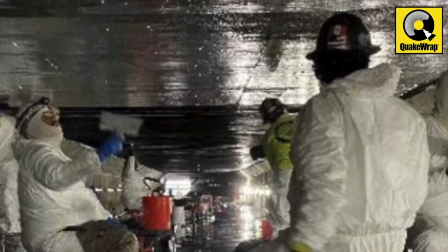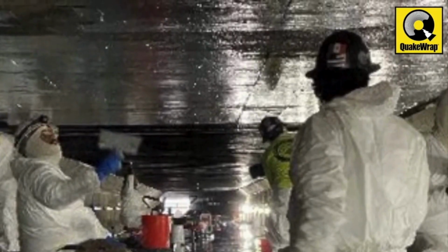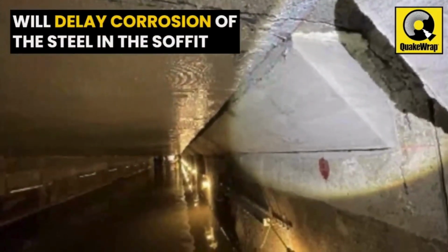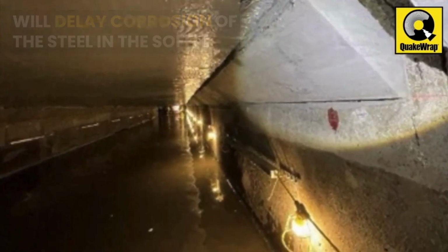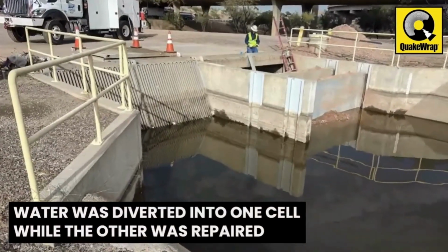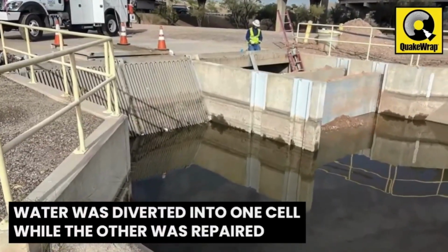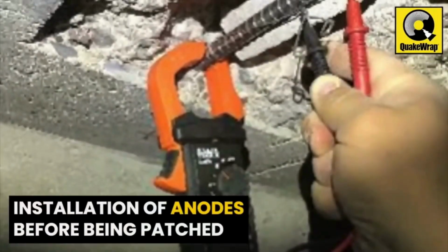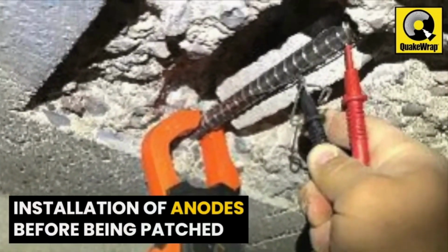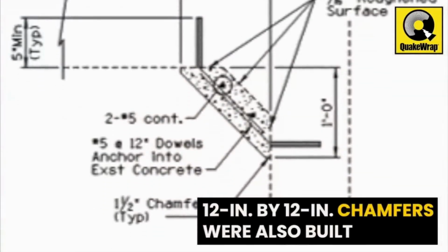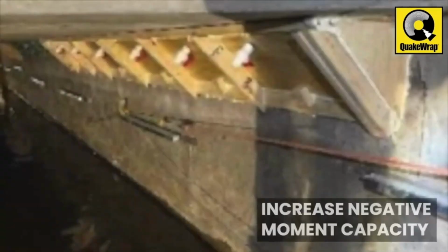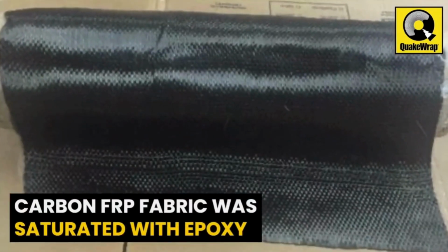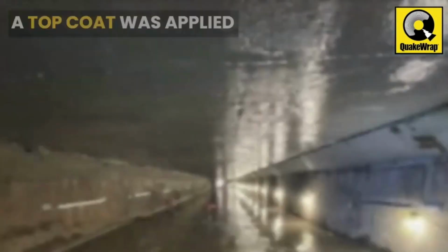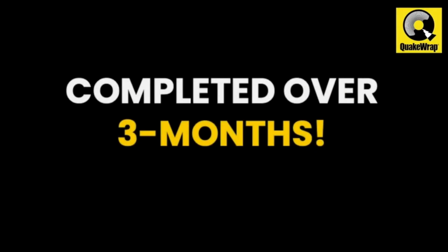Although this provided significantly higher strength than necessary, the complete coverage of the soffit would provide an impervious protective layer that will delay corrosion of the steel in the soffit. To facilitate the construction, water was diverted into one cell while the adjacent culvert was being repaired. Construction included installation of anodes before the concrete was patched. 12-inch by 12-inch chamfers were also built along the edges to increase the negative moment capacity of the slab. The 24-inch wide carbon FRP fabric was saturated with epoxy in the field and installed, and a top coat was applied. The project was completed over a period of 3 months during the low flow season.